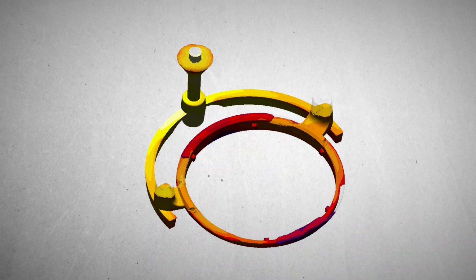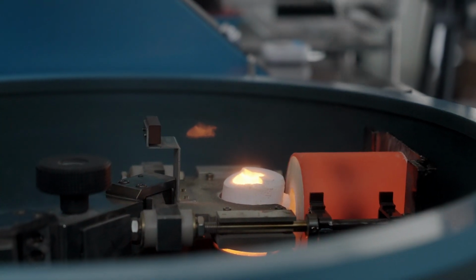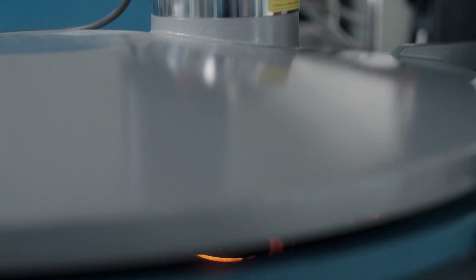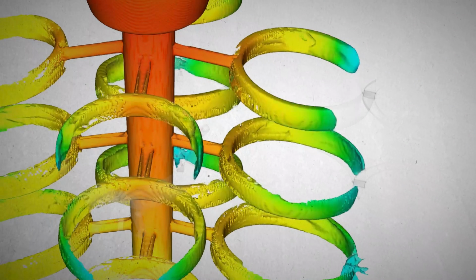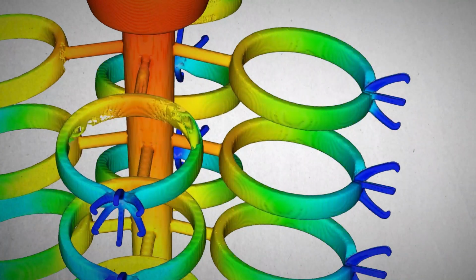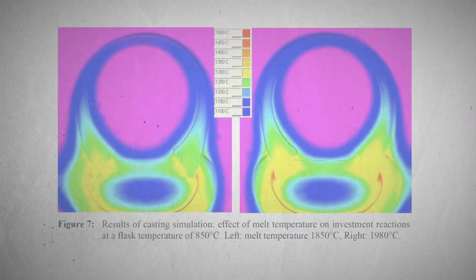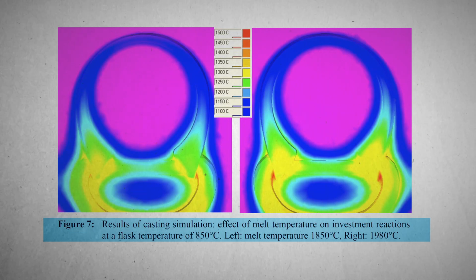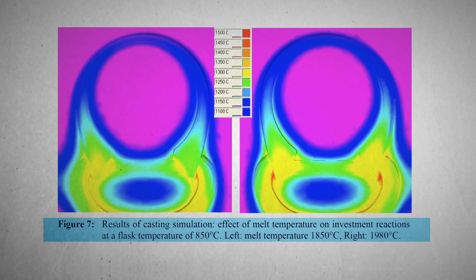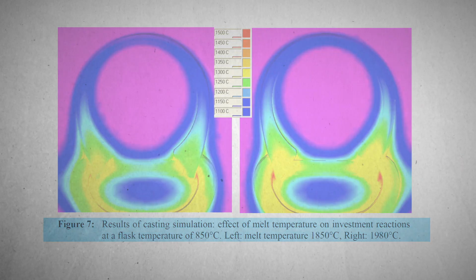And this time buffer is especially important for platinum because its melting temperature is significantly higher than the flask temperature, which means heat is lost the moment the metal leaves the crucible and goes into the cooler environment. The superheat helps to counter the heat loss, acting as a thermal reserve to make sure the metal is hot enough that it will flow and fill even when heat is lost along the way. Figure 7 in Dr. Ulrich's paper illustrates how heat is retained when we're casting at a superheat of 1980 Celsius.